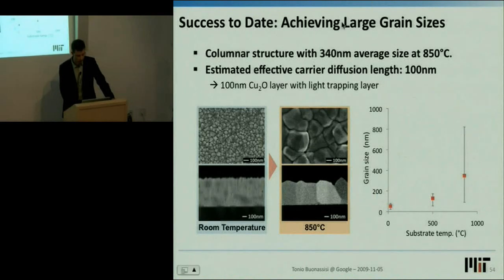For example, this one, a cuprous oxide earth-abundant solar cell material. We have a layer somewhere in the order of 100 nanometers thick, and we're trying to achieve grain sizes in the order of 500 nanometers or more. You can see that we've managed to increase it quite a bit.